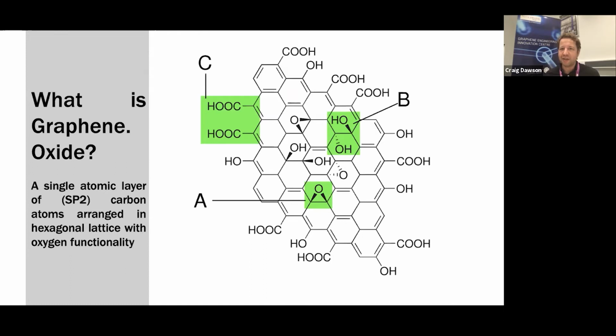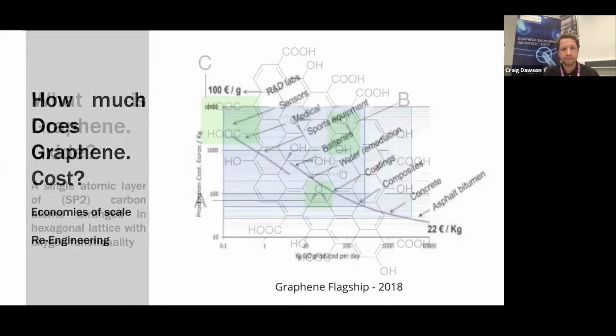And graphene is hydrophobic, so you can't put it within aqueous systems. Graphene oxide becomes hydrophilic, so we can use it in aqueous systems. So where that's appropriate, we can use this material. We can also functionalize this material quite easily, so we can change some of these chemical groups into other chemical groups, or systems can interact more readily with those chemical elements of the graphene oxide, whereas graphene as a pristine material is very chemically inert, and that's not quite as easy to do.